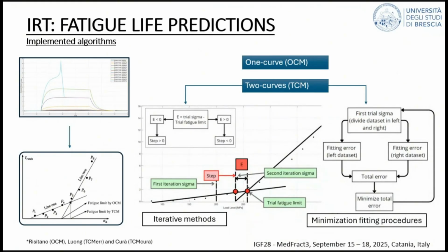We focused on the first one, which is the 1-curve method, which essentially does not consider the first part of the test results and focuses only on the area where the thermal index varies more significantly. And then there are the so-called 2-curves methods that can be implemented in different ways, but basically you fit both parts of the diagram with different lines.